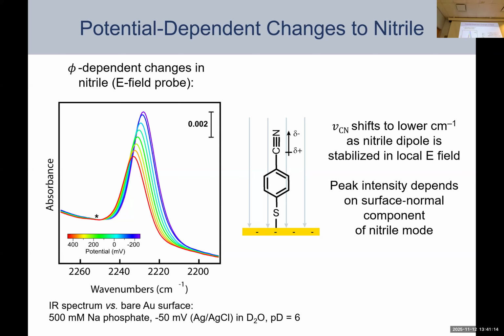Okay, and so you can see that here. These are SEIRAS spectra of the nitrile on our gold film, and you can see that the maximum wave number actually shifts as you go from positive applied potentials in red to more negative ones in purple. Okay, so there's a shift to lower wave numbers here, consistent with the fact that we're stabilizing this nitrile dipole. Another interesting feature here is that the relative size of this peak is growing, and that's explained by essentially a reorientation of the molecule on the surface. This is a really clean and classic example of that fact. So as you go from more positive applied potentials to more negative applied potentials, this molecule is actually standing more upright. And so more of this nitrile stretch becomes normal to the surface.